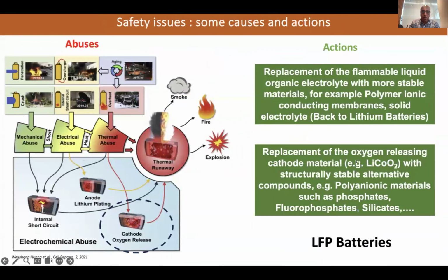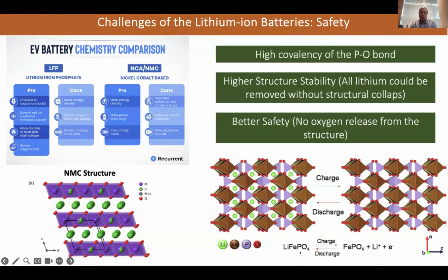So there are many causes of this safety issue. There is mechanical abuse like penetration or crush. There is electrical abuse like short circuit. There is thermal abuse. And as you see, this abuse can induce smoke, fire, explosion. And you see the cathode oxygen release. This is what I am saying. The cathode oxygen release comes from the oxide, from the NMC-type electrode. And now this justifies why LFP phosphate is good for safety in lithium-ion batteries. To make it clearer, why we have this good safety for phosphate batteries: because of the high covalency of the PO bond, high structure stability, and better safety.